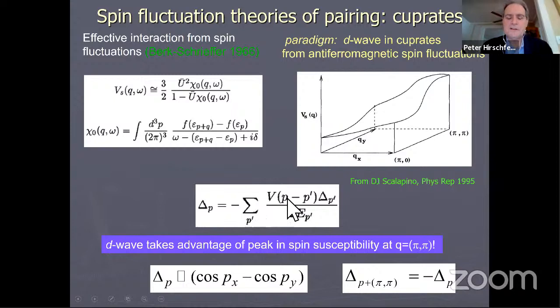If you put a constant interaction in here, even a constant attractive interaction, if you put a constant repulsive interaction in here, you cannot solve this equation because the gap will be one sign and you have a minus sign here, and E_P, that's the quasi-particle energy, is always positive. So you need to have this V of P minus P prime change sign from one point in the Brillouin zone to another. And that's in fact what it does in the cuprates.